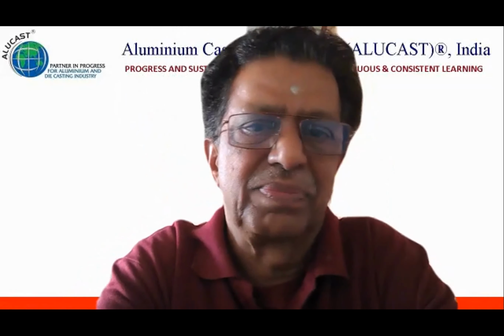Okay. There is a question from Mr. Vijay Jangam. We have observed microporosity after machining for LM4 material in the GDC process. So how do we control it? Microporosity, again going back, hydrogen. Please remove hydrogen: degas, degas, degas, nitrogen bubbling, density index. Same answer, let me repeat again. Degas thoroughly. Check the density index. If it is less than 1.5, go ahead and pour it. Zero porosity is impossible, but you can get extra quality at the first level, beautifully, with proper degassing.